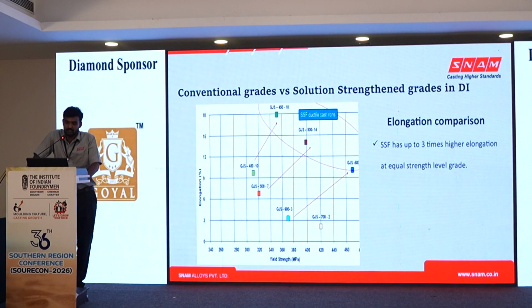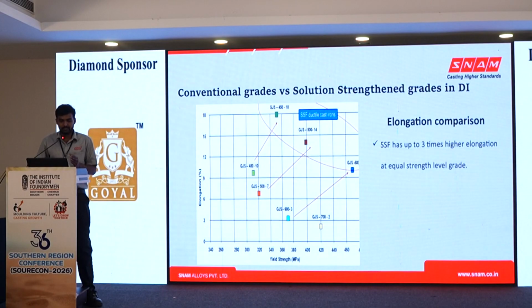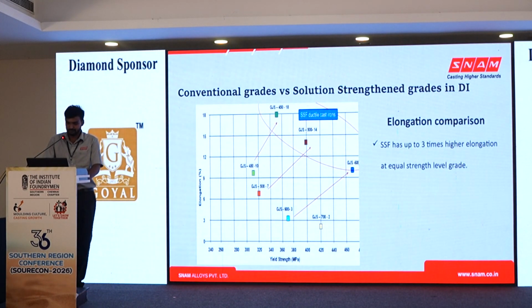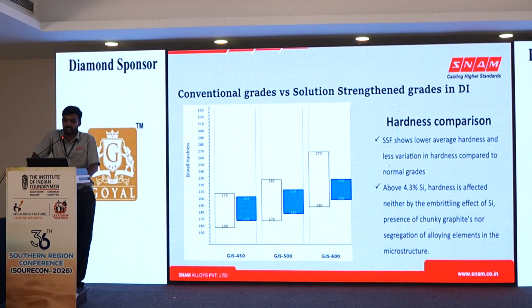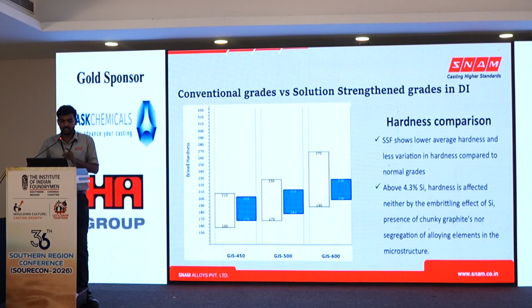So when we see the elongation, we can see almost three times higher when compared to conventional grades. For example, if you take a 600 grade, the elongation for common conventional ductile iron is only 3%. But in case of SSFDA, we have 10% of elongation. So when we see the hardness comparison, we can achieve lower average hardness with minimal variation in SSFDA compared to conventional grades. In conventional grades, we have larger variation in Brinell hardness number.